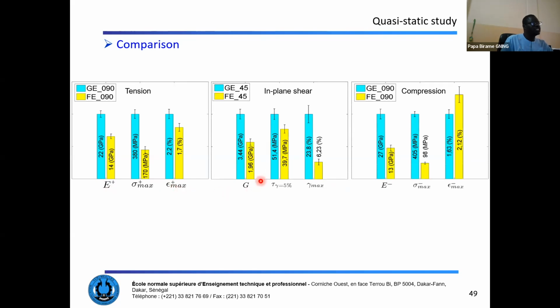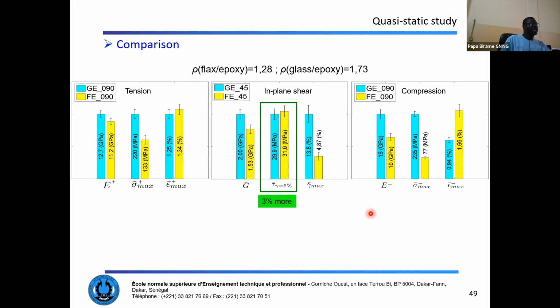So let's compare the properties in tension of glass epoxy 0/90 fibers and Flax epoxy 0/90-degree oriented fibers. So we see that the glass in blue have higher modulus, higher strength, and higher maximum strain. In in-plane shear also, we have the glass which presents more important properties in the shear modulus, the shear strength, and the shear strain. Also, in compression, the difference is the more important. This can be